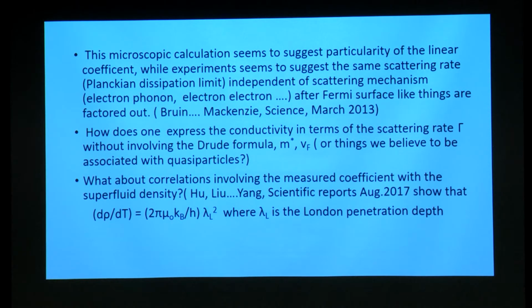So this microscopic calculation seems to suggest a particularity of the linear coefficient. That is, the coefficient of the T in the linear dependence of resistivity on temperature depends on the material. But experiments seem to suggest the same scattering rate, independent of the scattering mechanism.